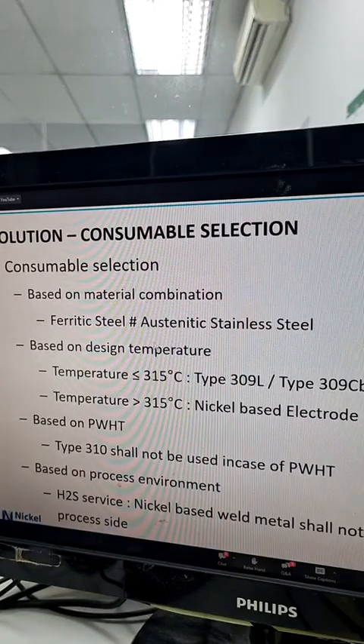And regarding the consumable selection, based on the material combination, you need to plan things around, like whether it's a ferritic steel to austenitic stainless steel, and what is the temperature my weld will be subjected to. As a thumb rule, less than 315 you can go for a 309L type, and more than 315 nickel is preferred. 310 is a good option, but when you have PWHT, that is not the right option. You need to consider those aspects.